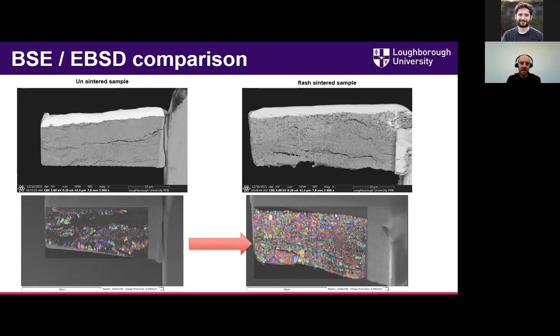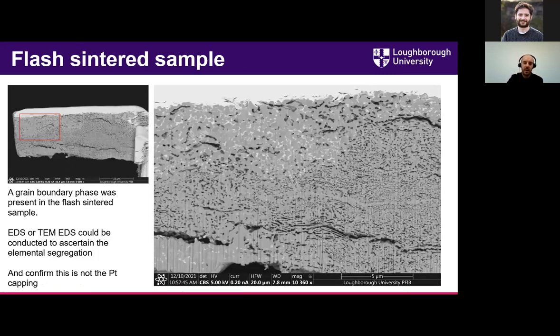So did we actually manage to flash sinter the material? One way of checking this is to look at EBSD mapping and see if we've increased the grain size and how indexable the grains are, like how crystalline the material is. So we started off with the unsintered sample on the left here. And after flash sintering, you can see a lot more grains are indexable, and also the grain size is increased, with much larger grains across the sample. And here is a zoom in on an area. Again, the grain size is significantly increased, and there might be a grain boundary phase that's formed.